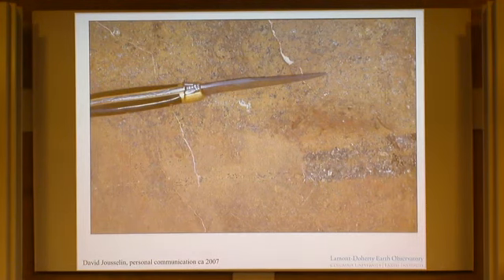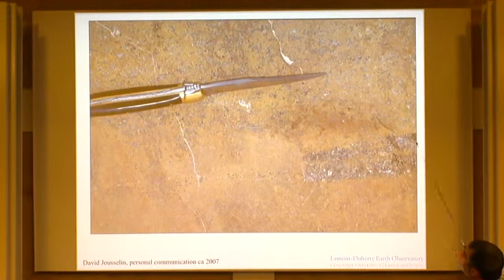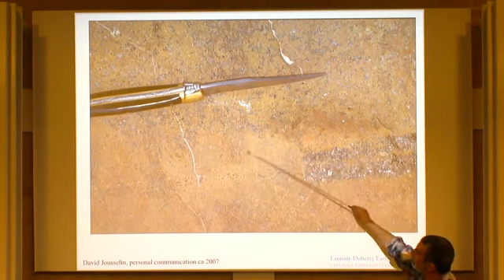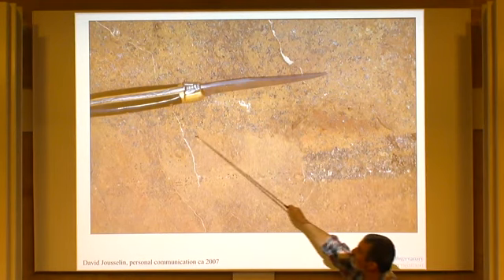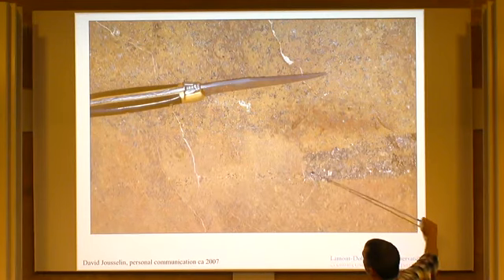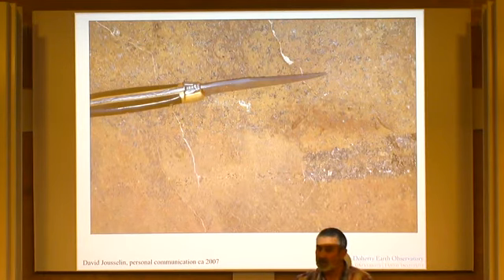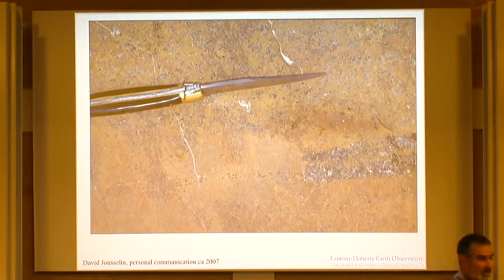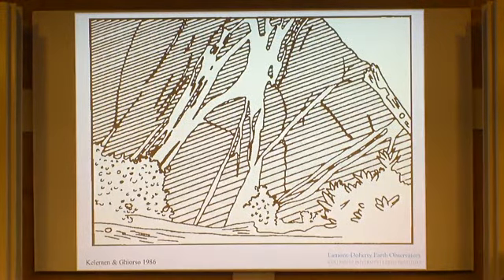Here's an actual photograph of that kind of texture. So here's a pyroxene-rich band, this is peridotite. This is a dunite, with pretty sharp boundaries, typical on the grain scale. And you can see this little trail of spinels leading out from where that pyroxene-rich band used to be. This is my very first replacive dunite up in the Cascades.